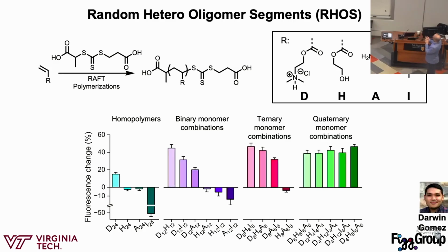And then we have the different monomers, with D, H, A and I, and this number is the number of monomers. So this is an oligomer of 24. With the cationic monomer, we actually get a little bit of increase in fluorescence. This is pretty widely known, that cationic polymers can bind to anionic proteins. That makes sense, right? But with the other monomers, they either don't do anything or denature it. But then as we start to go to binary, ternary, and quaternary monomer combinations, you see we're getting up to about 50% fluorescence increase. And it really depends on having these different monomers in combination where we're getting the saturation. Like this combination of D and H gives us a pretty high fluorescence change.